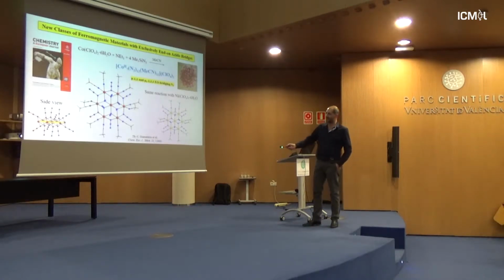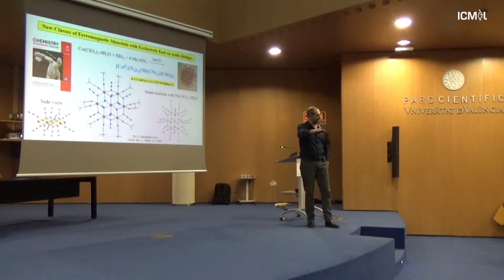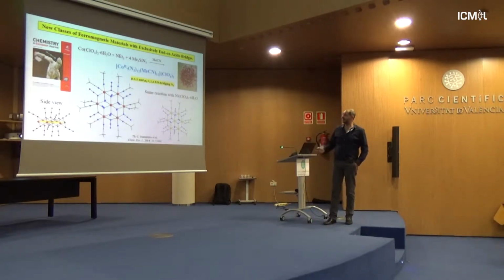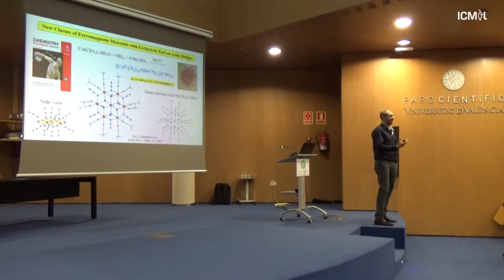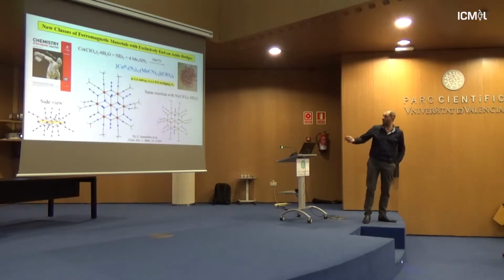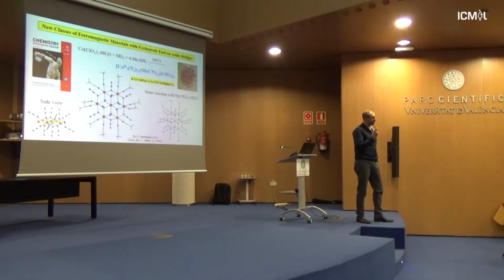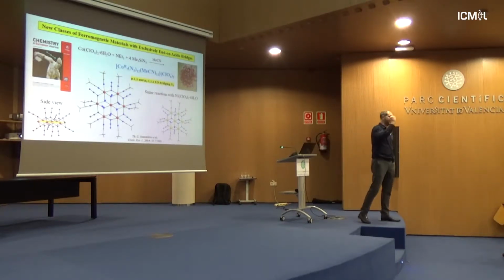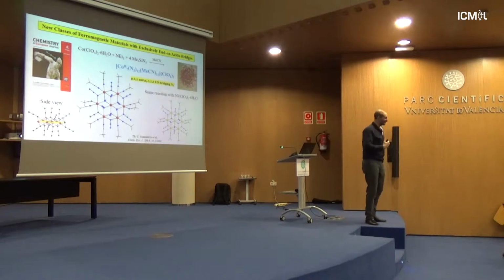You can see the side view here, how the azides are displaced above and below the plane. It's like a layer structure. And most importantly was to understand why we were able to crystallize that compound. The reason was the base. So the system needed the base in order to generate hydroxides in solution. So essentially, the activation of trimethylsilyl azide comes from the previous generation of hydroxides in solution.